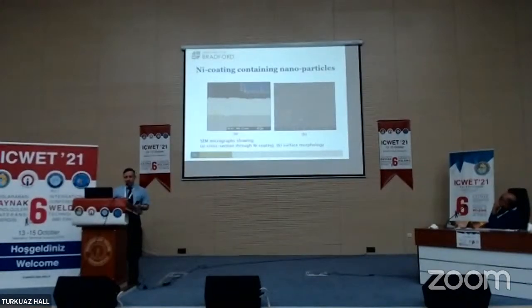These coatings are produced by electrodeposition, and the process is sometimes known as electrophoresis because these particles become trapped with the nickel atoms and they move to the substrate surface together. So the coating itself has a very fine grain structure.